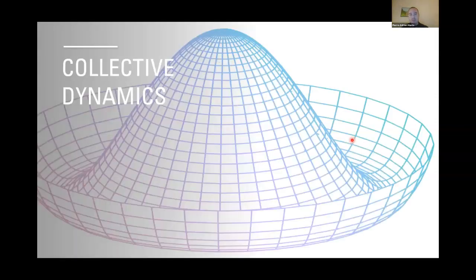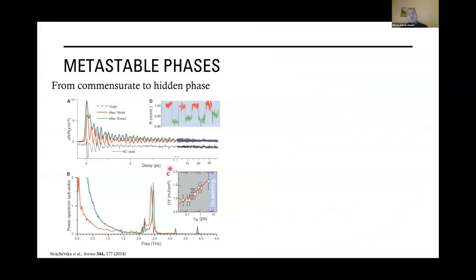So in the second project, we are caring more about the collective dynamic, or the coherent dynamic. And this is all stemming from this paper where they demonstrated that through the absorption of a femtosecond pulse, the system can be driven into a hidden phase. And one of the main results of this paper is that phases in charge density wave can be characterized by their vibrational spectra.